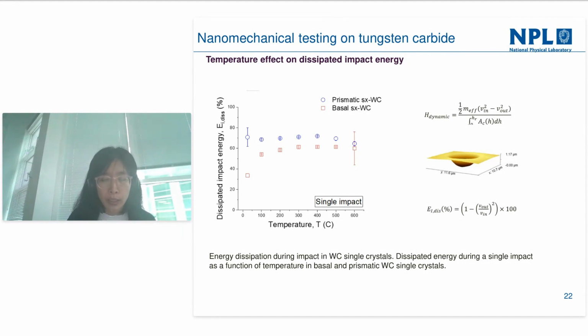Knowing the inward velocity, which is when the impact occurred, and the outward velocity, which is the first rebound velocity, we also calculated the dissipated energy, which is a good indication of the degree of plastic deformation in the impact test. For both basal and prismatic systems, the dissipated impact energy is given in the figure on the left. As you can see, for the prismatic orientation, the dissipated energy stayed at a constant level of about 70%, while for the basal plane it increased from about 36% to 60% with increase in temperature.